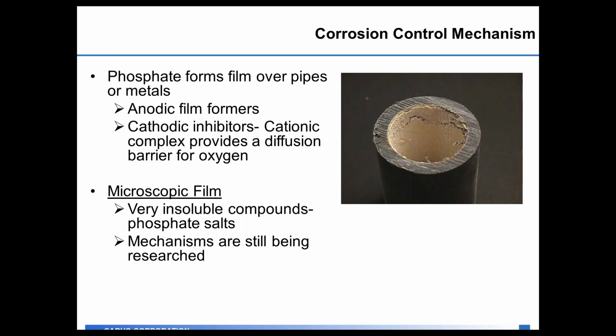There's been a lot of research done over the years on the corrosion control mechanisms involved with phosphates. What we do know is that phosphates form films over pipes or metals out there in the distribution system. They are anodic film formers. So the orthophosphate is slightly negatively charged and forms a film on the inside of the pipe by attaching to the metal. Polyphosphates can also act as a cathodic inhibitor, and they provide a barrier between the metal pipe surface and oxygen to prevent that interaction of the oxygen with the metal pipe surface.